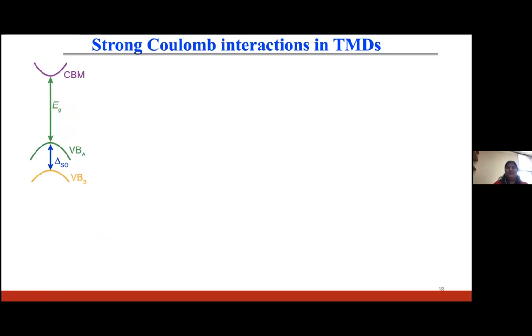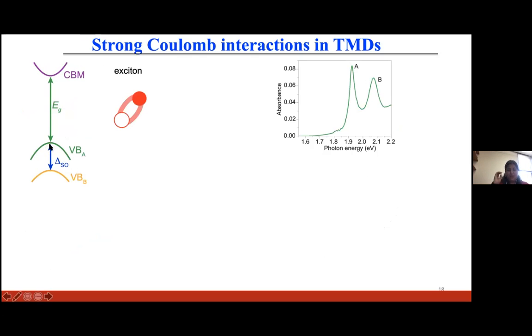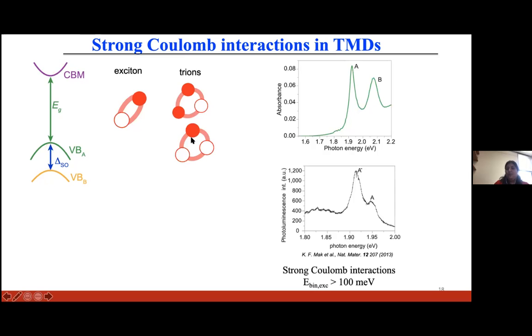In addition to that, the TMDs also have very strong Coulomb interactions, which means if we excite the carriers from the valence band to conduction band, then this electron and hole can form a strongly bound quasi-particle called excitons. And if we n-dope our sample by putting in a lot of electrons, then we can also have a strongly bound electron-hole-electron complex formation, and these bound particles are called trions. Both excitons and trions have been observed in optical measurements. And so the question that we had was, can we unlock these excitonic and trionic effects in this WS2 using ARPES?